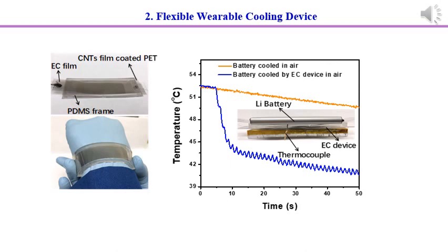The EC polymer film did not show any sign of electrical breakdown or damage after 30,000 cycles of charging and discharging. Comparing with other solid state devices, we achieved a heat flux of 30 mW per square centimeter with an applied electric field of 66.7 MV/m across the EC film, corresponding to a specific cooling power of 2.8 W per gram. We demonstrated the benefits of the inherent thinness and flexibility of our cooling device by conforming it to a smartphone battery under high workloads. The battery heated up to 52.5°C. When allowed to cool in air, the surface temperature decreased by 3°C in 50 seconds. After the flexible EC cooling device was attached, the surface temperature decreased by 8°C in the first 5 seconds with EC cooling activated.